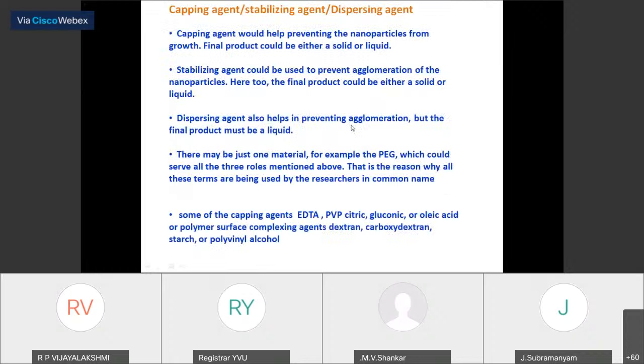When you go for the chemical co-precipitation method, while the reaction is taking place, we have nucleation. In the nucleation, the growth process takes place, and the growth process takes place in all directions. It is not possible to grow the crystal with the required size and shape, so it will grow in all directions.